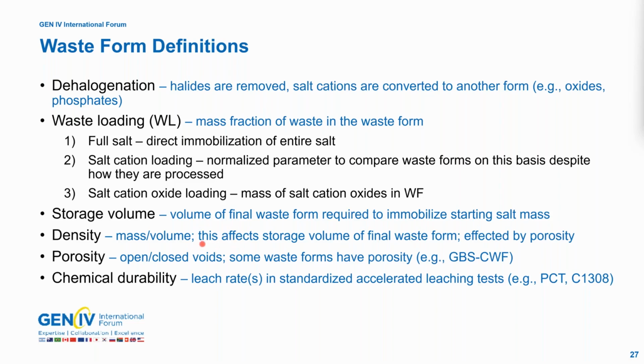Density, of course, is mass over volume, and this is a part of the storage volume calculation. And the higher the density waste form, the smaller the volume of waste form in a repository. So this can affect cost, it can affect a lot of storage issues that could arise. Porosity is a way of comparing waste forms that have porosity, such as the glass bonded sodalite, with things that don't, such as an iron phosphate waste form that I'll talk about later. So these are important when we're comparing one to another. And then there's chemical durability, which is the leach rate and standardized accelerated leaching tests that we conduct here at PNNL and Bill Ebert at Argonne National Lab, things like the product consistency test and the C1308 coupon tests that Bill runs.